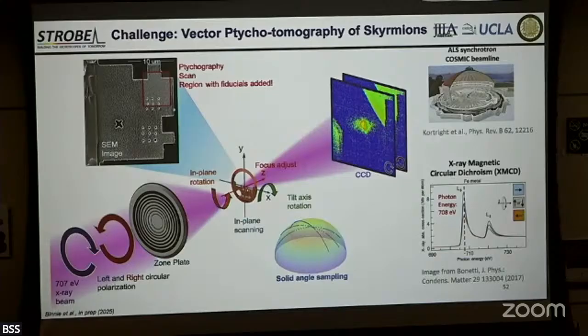So that was the trick. On the third effort, we finally figured out how to make this measurement right, which was to put in alignment fiducials. Otherwise you have no idea if the magnetic texture you're extracting is real. So for the alignment fiducials, there are little holes, both edges and holes, and this is a multilayer gadolinium iron sample on a silicon nitride membrane that's a little bit rippled. And in addition, there's stray light. All of this complicates extracting the image.